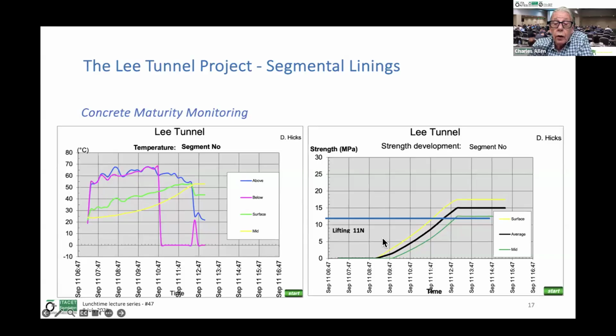Using this system, you can actually measure the in situ strength of the concrete. Here the concrete was cast approximately 7 o'clock in the morning, and 6 hours later, when it was demolded, you can see its strength. We required 11 MPa lifting strength, and you can see the average strength in the segment was 15. So by placing the maturity monitor into the last segment of each shift, you can determine what your strength is.